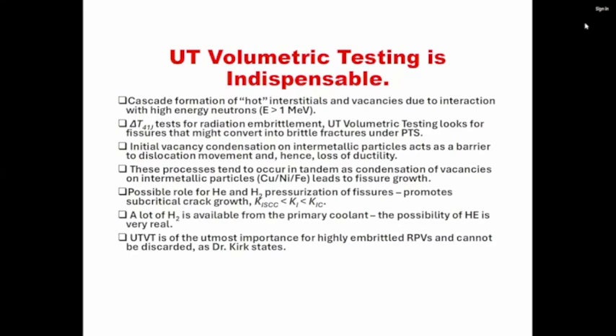Now, the UT volumetric testing is indispensable. First of all, we have to understand the cascade formation of hot interstitials and vacancies due to interaction with high energy neutrons. Delta T 41J is the test for radiation embrittlement. UT volumetric testing looks for fissures that might convert into brittle fractures under pressurized thermal shock. Initial vacancy condensation on intermetallic particles acts as a barrier to dislocation movement, and hence a loss in ductility. That's embrittlement.